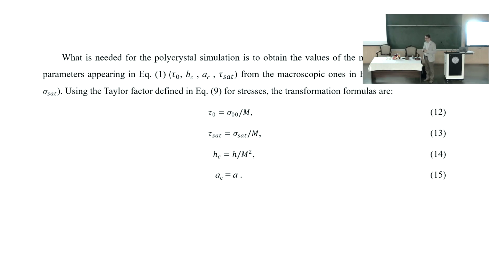No, but I simplified the thing. Actually, it was the author number 2, Satyavir. He was with me, and then he wanted to do some simulation of macroscopic strain hardening curve. I said, you want to simulate texture in asymmetric rolling, okay, but we need a strain hardening curve. So then he got a strain hardening curve in tension, fine. Then we have to first model this for tension to get the parameters, and then use those parameters in the asymmetric rolling texture simulation and all this.